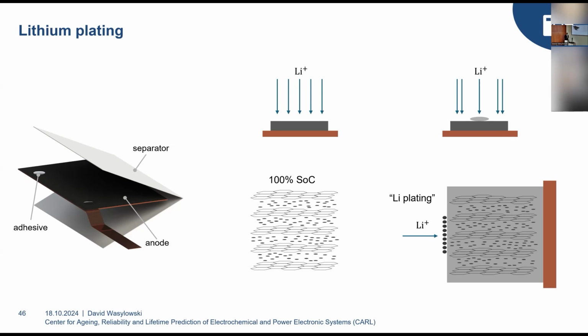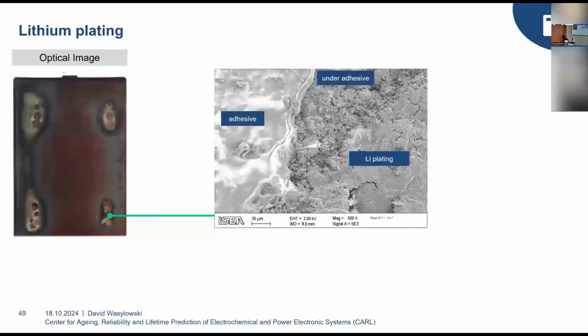So in order to prove this point, we did a scanning electron microscopy image that you can see here. So this is right at the border between the adhesive and the anode. And this is the border between this adhesive that you can see here. This is this shiny part. And if we just compare the side of the anode, so this is where we suspect this lithium plating, to literature images of lithium plating, we can basically see that they look very, very similar. So we are in fact validating that this is most likely actually lithium plating that we're seeing here.